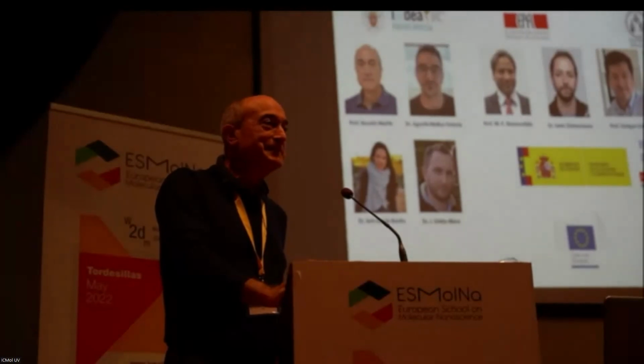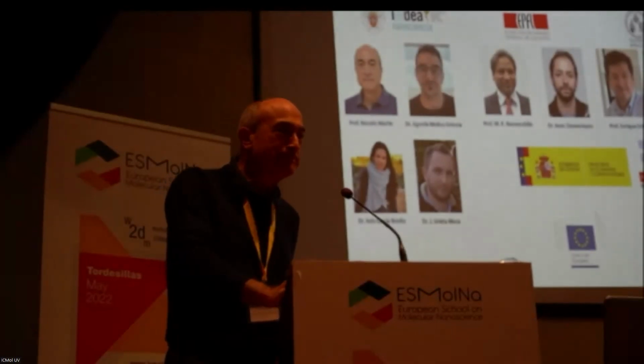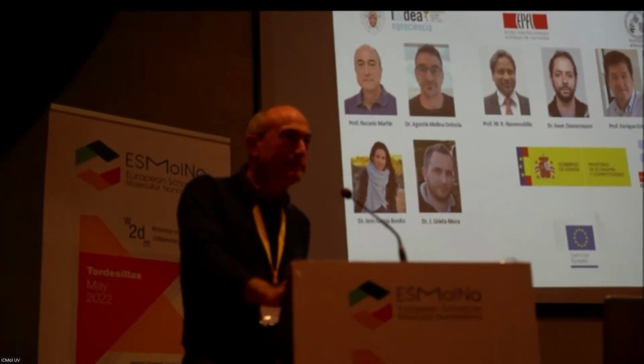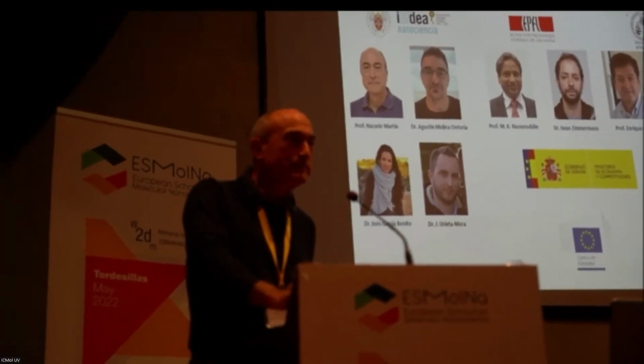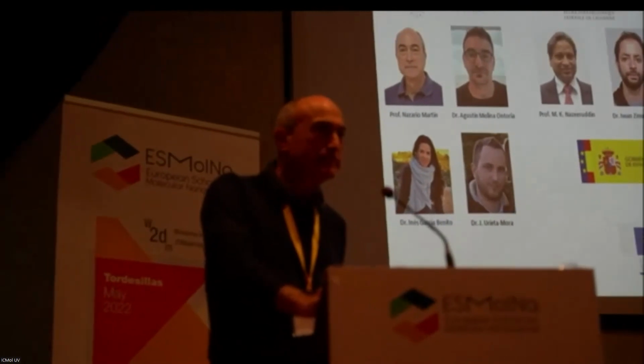Sorry if I missed it at some point, but the best material is evaporable, because at the very beginning you're thinking about solubility, but actually you want to be very stable. So something which is very insoluble but very easy to evaporate is the best material for this type of devices, or am I wrong? No, well, all these materials in particular, as they are spiro systems, they are not planar anymore. Because of that, they are quite soluble in organic solvents.